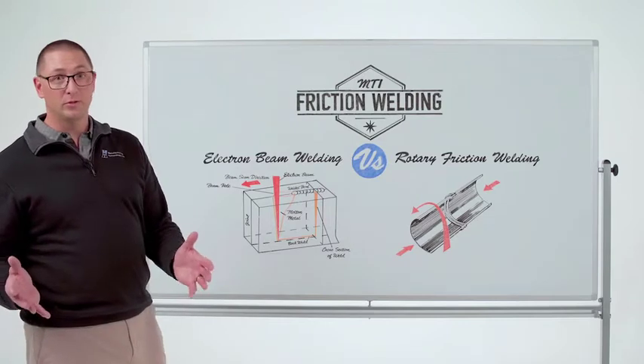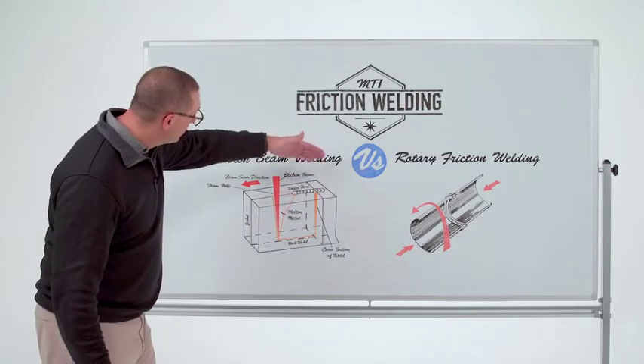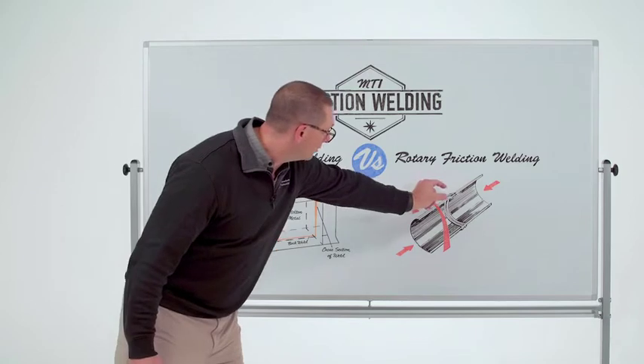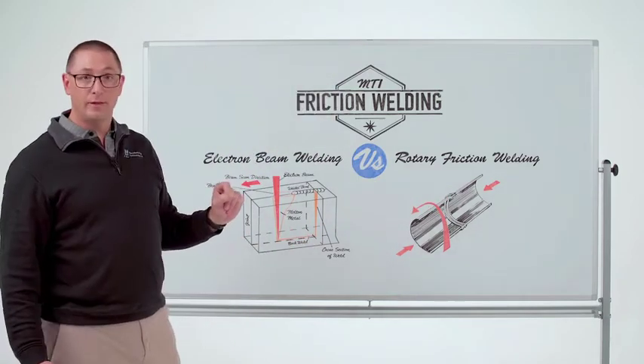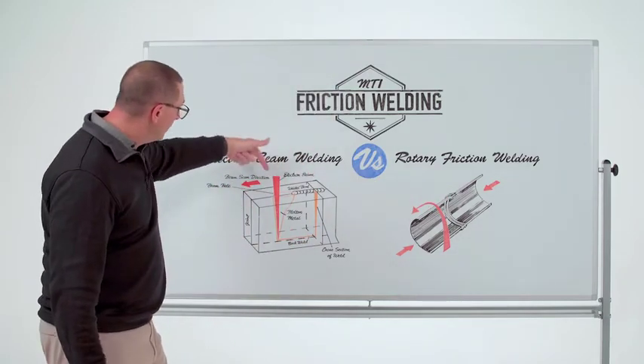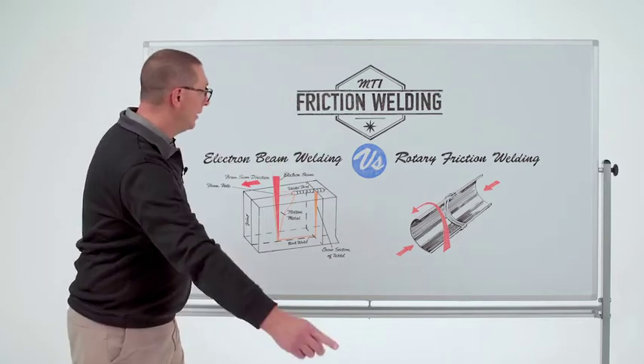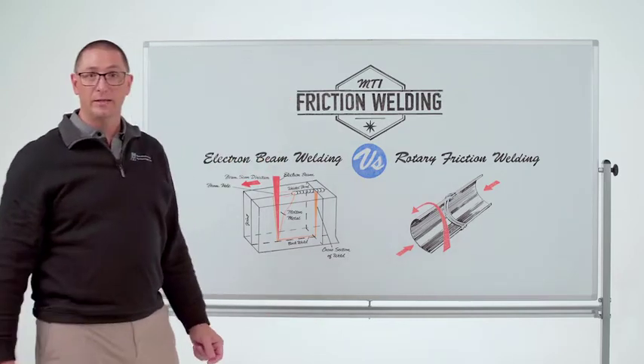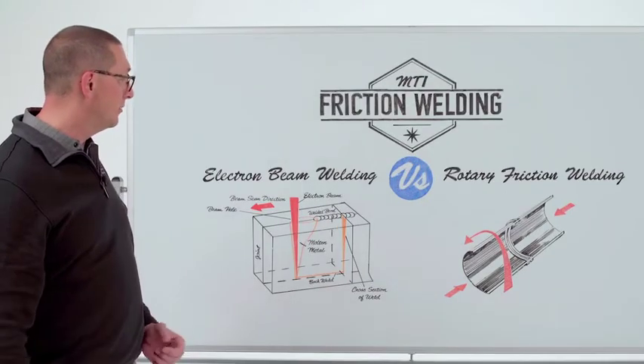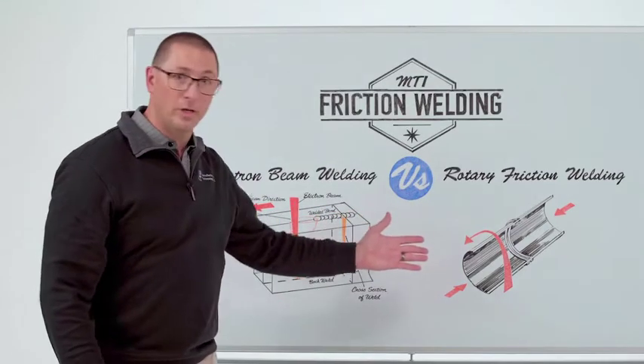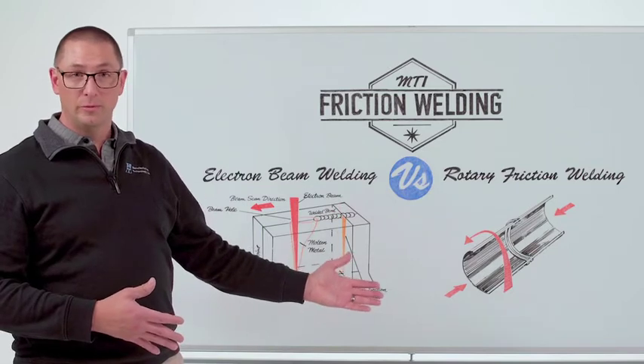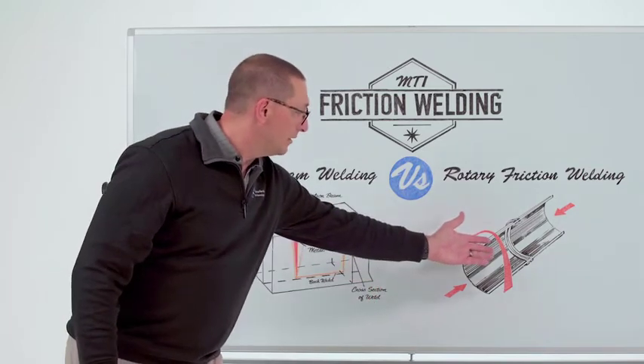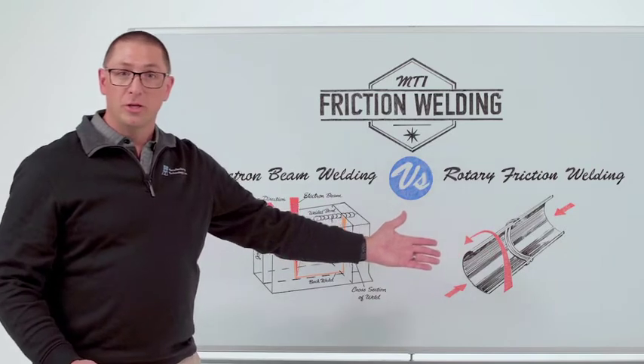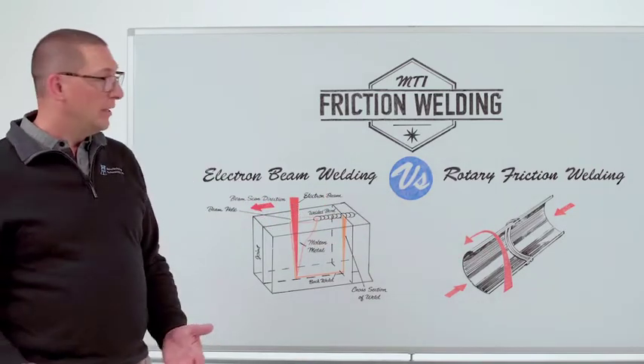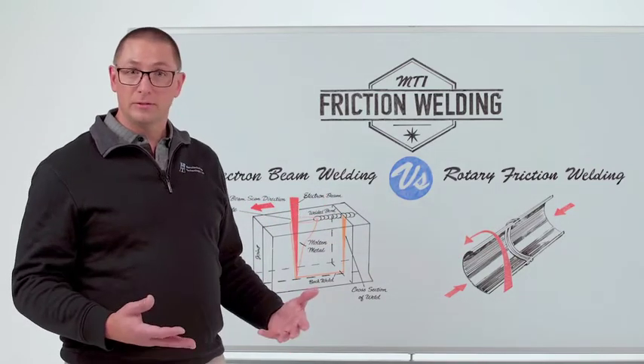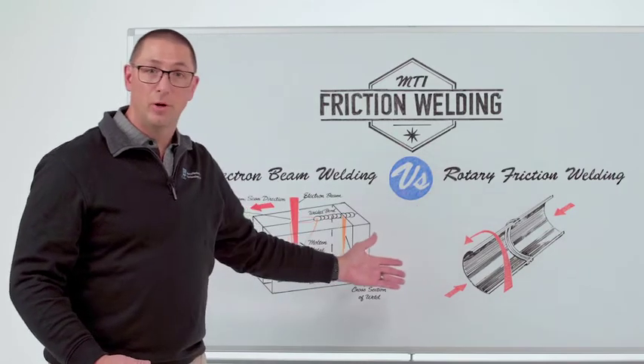Now let's compare it to traditional friction welding. If you would imagine this piece being the section view of a thin wall tube, and this electron beam is actually making a traverse along the outside diameter of the tube, that's how this could be looked at. Traditional friction welding, you don't need to do the pre-weld machining, but the friction weld is going to leave a weld flash that may need to be removed. And in order to get the tight tolerances that you might expect, you're probably going to do some post-weld machining.